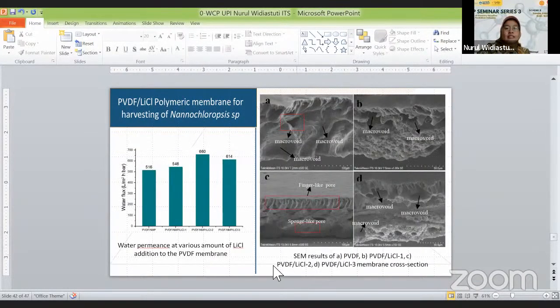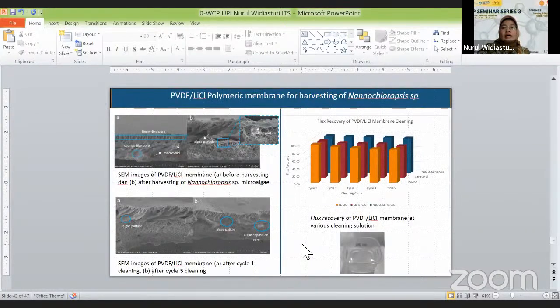And then we see the water permeance at various amounts of lithium chloride addition to the PVDF membranes, and the SEM result between the PVDF itself and the PVDF with lithium chloride. And we also conducted cleaning of the membranes after we used them for harvesting Nannochloropsis microalgae. We use three kinds of cleaning agents: citric acid and sodium hypochlorite, and also we combine sodium hypochlorite and citric acid here.